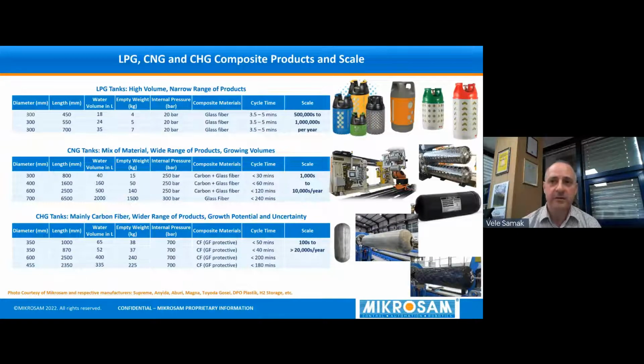And finally, this is an established market with the different applications on the CNG tanks, but the hydrogen tank is one that's in a lot of demand, a lot of growth potential, and we're all waiting for that hockey stick to kick in. But the crucial point here is that it's largely carbon fiber driven material on the composite tanks, much more material per tank. So sometimes you have a lot of material per tank going in there. And cycle times are, of course, going to grow as a function of that requirement.